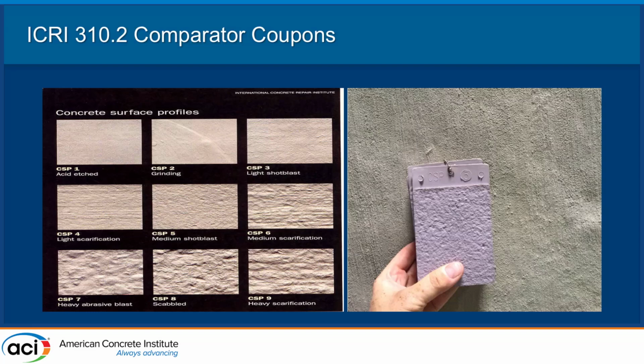So if you're specifying a range from 3 to 5, then when the surface prep is completed, the inspector or whoever wants to verify that, they can actually take these rubber coupons and compare it to the surface to verify that the actual surface prep meets what is specified or what is recommended by the manufacturer.